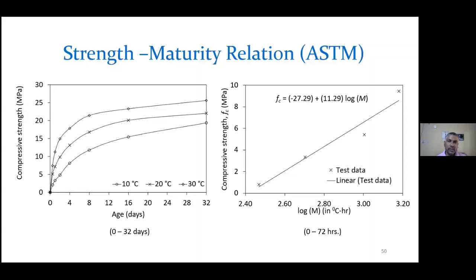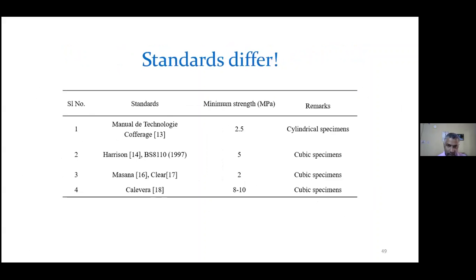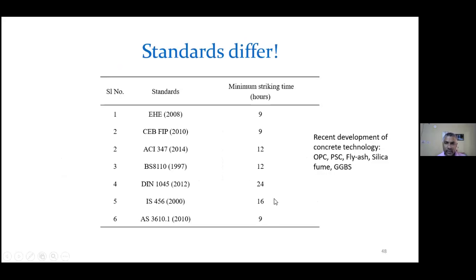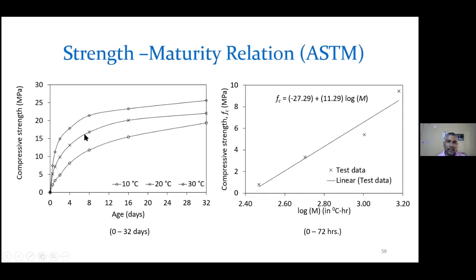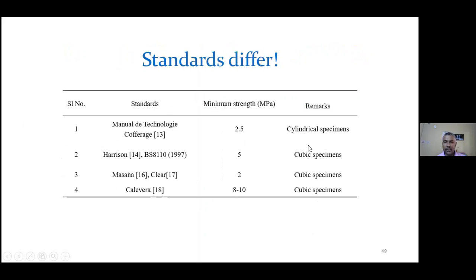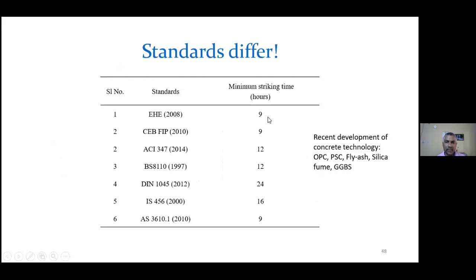Now we tried with our instrument, and here one interesting thing we did: everything is happening between 9 and 24 hours. The strength maturity relation usually considers 0 to 14 days, an early age property, but 14 days is too long. So to have more accuracy, we developed the strength maturity relation only for 0 to 72 hours. We used only the 72 hours data for a finer strength maturity relation, because we felt that it will be within that range.